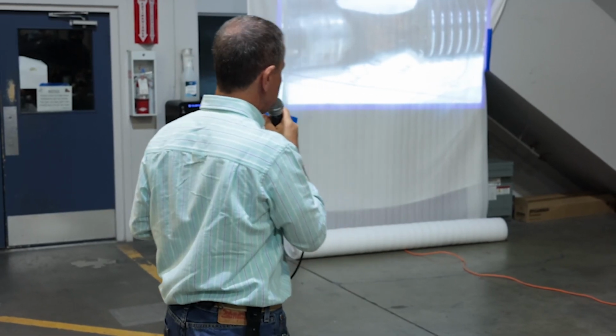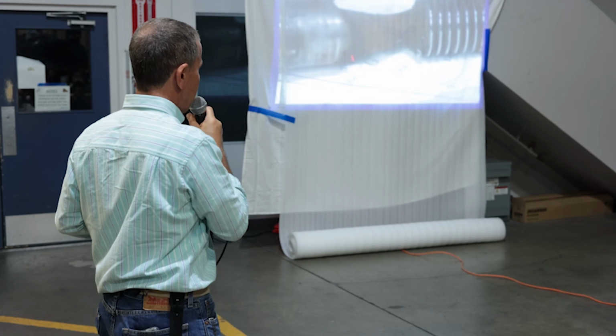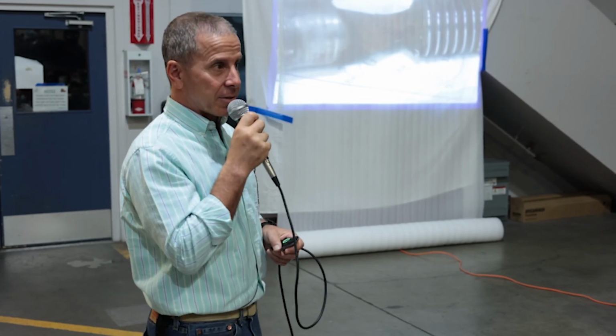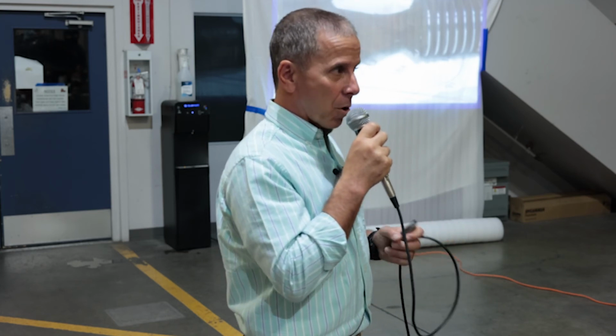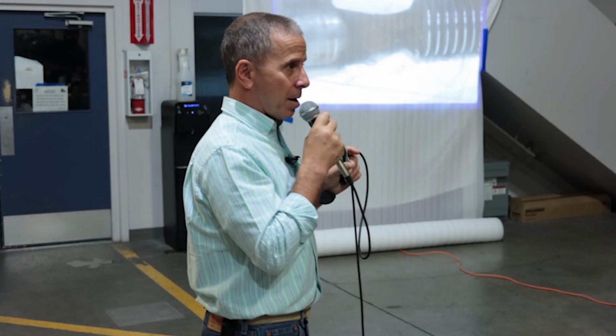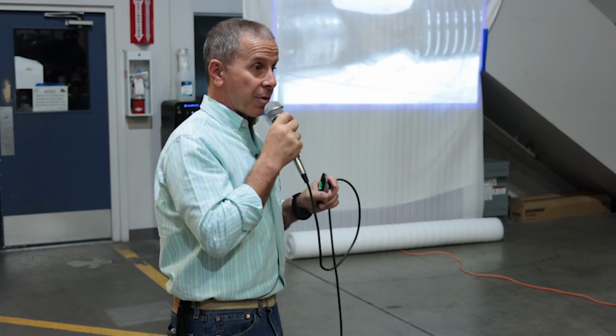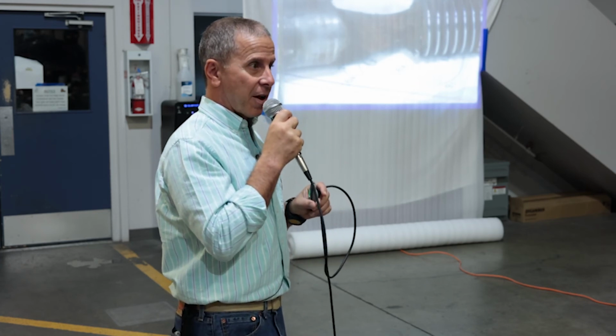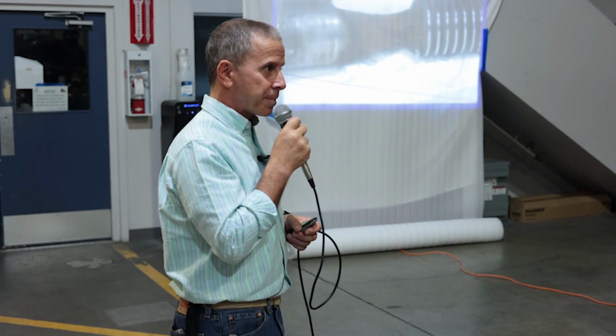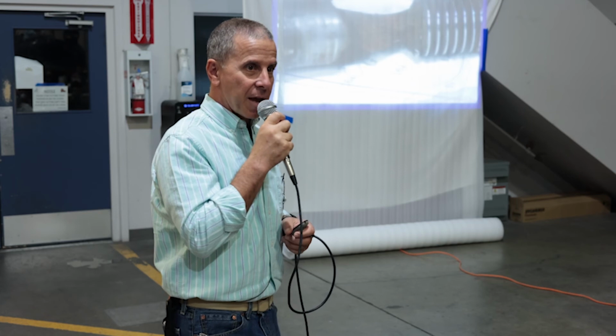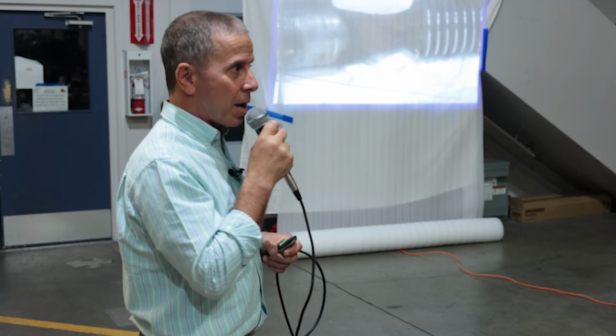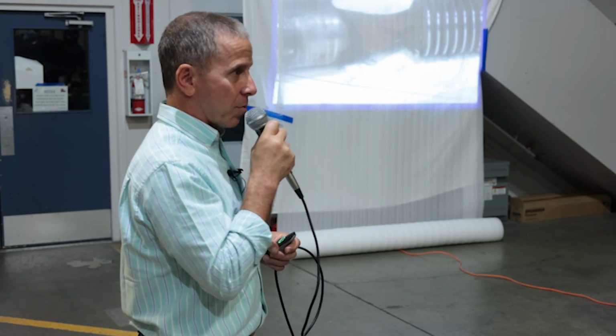So this fastener, the shank on this fastener, you can see it's what we call hourglassed. That is where that fastener passed through a fiberglass hull. Water penetrated into that void and remained there in a stagnant fashion. It wasn't being turned over, so the oxygen in it got used up very quickly. And now that stainless steel doesn't have exposure to oxygen anymore, it becomes active and begins to corrode.